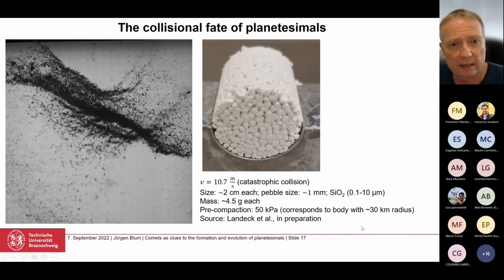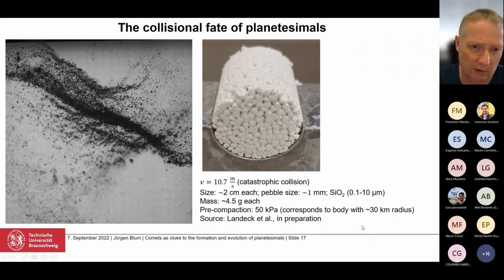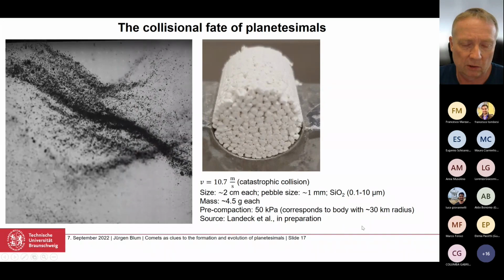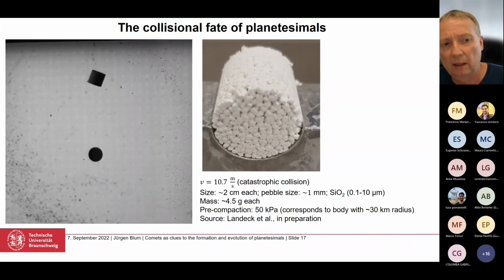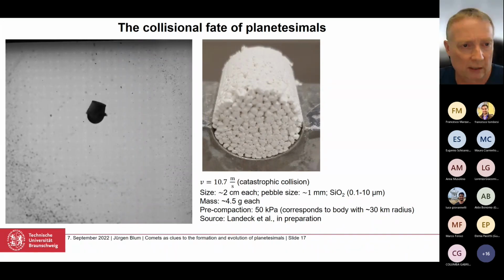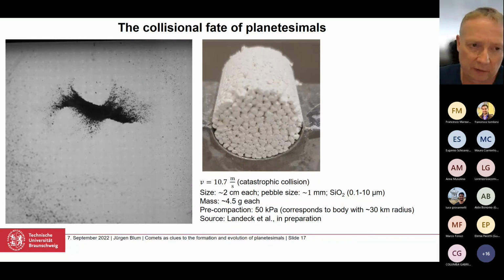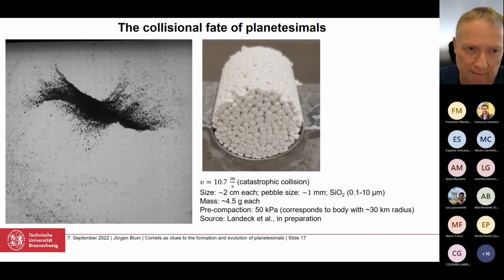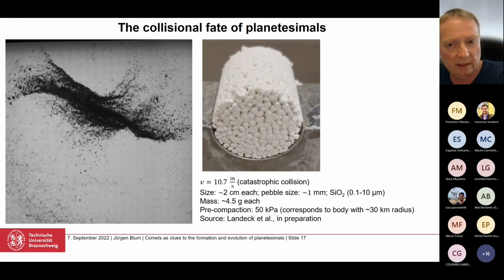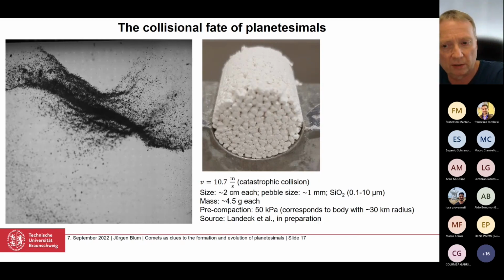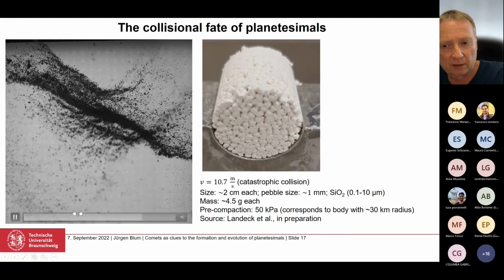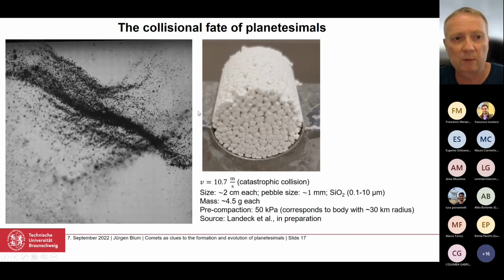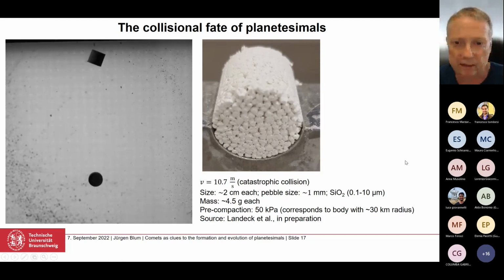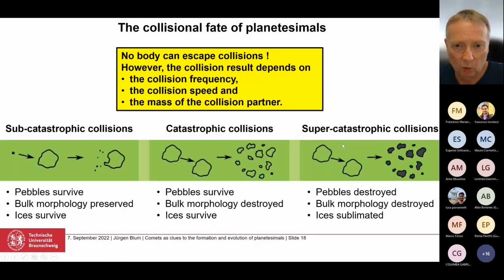And what you're seeing here is a so-called catastrophic collision. Catastrophic has two meanings. First of all, the biggest remnant after the collision is certainly less than half the mass of the original ones. That's one definition. And the other definition is we're still having the pebbles intact. What you're seeing here is individual pebbles flying away. They were not destroyed.